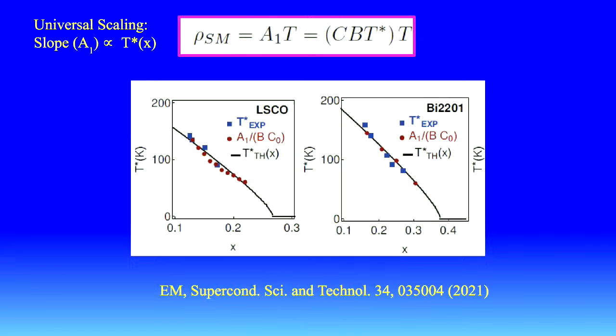You see here is a plot of the slope A1 divided by BC0, slope divided by BC, which is proportional to T star. So you see here the red dots are slope divided by BC, this is our expression for the pseudo gap, the blue squares, and the experimental is the black dot. Okay.